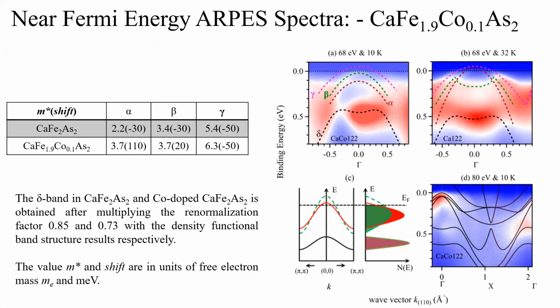What I meant by the correlation is in the DFT calculation that we do. In this case, I have not included the correlation part. These are single particle calculations, so we don't have correlation in these calculations. You add U from outside and then you include the correlation part. How do I know that this compound has correlation? It's because the dispersion relations for these bands are not matching the experimental data, and the m star values that I get from the calculation are much lower than the experimental values. So m star is high whenever there is a large correlation.